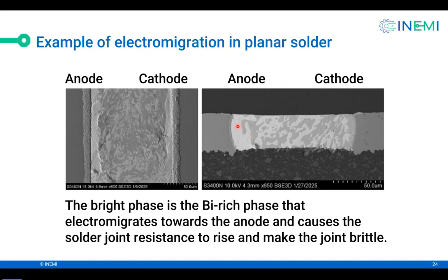because bismuth is the resistive phase. The gray region is more conductive. So when bismuth segregates at the anode, the resistance goes up. So that's why we can use resistance of a solder joint as a measure of electromigration.